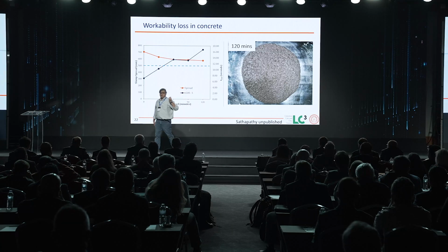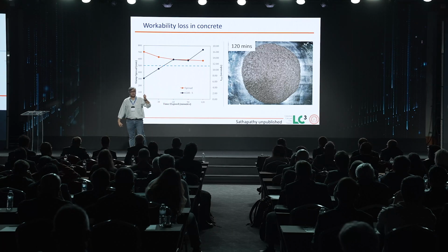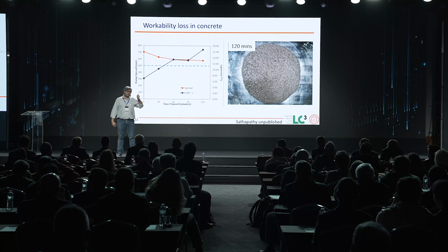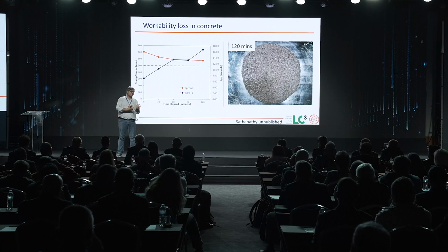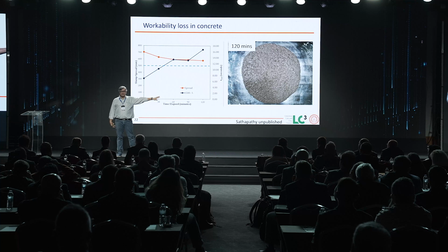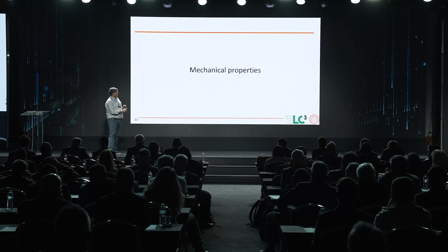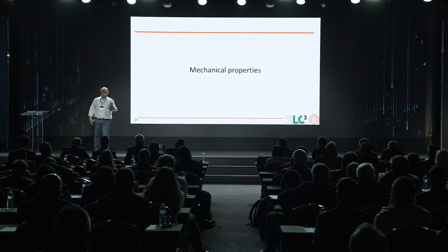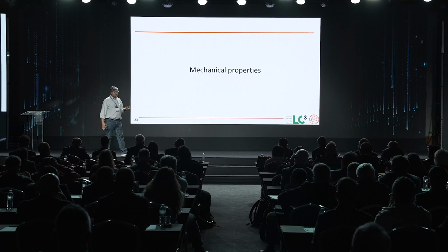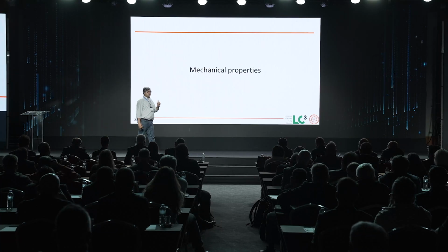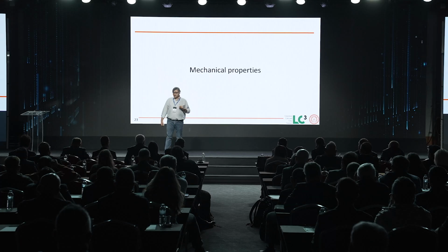This is using LC3. If you're asking me why it does not look red, because by the time you make the concrete, the red color is diluted because of the gray color of the sand. And by the way, this clay was also a higher grade clay, so the workability loss was worse, but the iron was less in this particular case. So that's about the workability. We can handle it. I promise you we can handle it. And if you're having issues, talk to us. We will help you handle those issues.